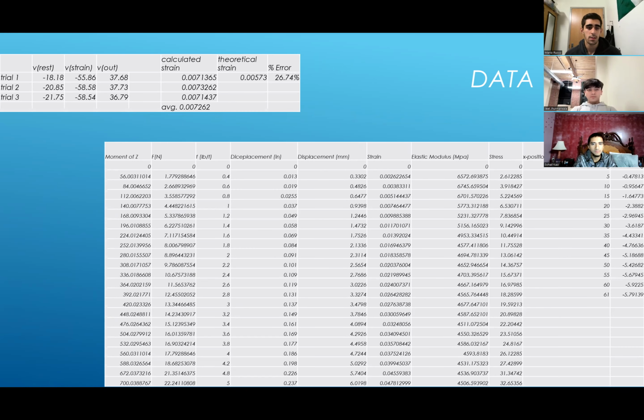So, as G just prefaced, for the first part of the experiment with the strain gauge in the dead center of the sample, because that is the point with the maximum displacement, we were able to calculate strain three separate times, with the average being 0.007262, and that had a 26.74% error. Relatively, not perfectly accurate, but still within reasonable realm.